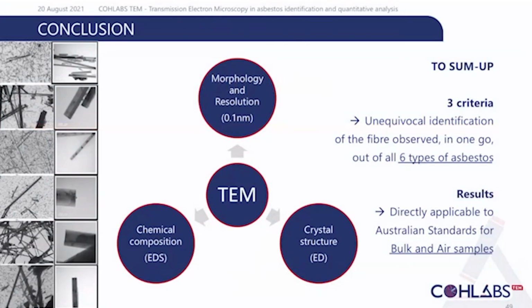So in conclusion, TEM gives access to those three criteria I've just mentioned: the chemical composition given by EDS, the crystalline structure given by the electron diffraction, and the morphology thanks to the high resolution of this microscope, down to 0.1 nanometers. Those three criteria give an unequivocal identification of the fiber observed in one go, and out of all six types of asbestos. And the results we have can directly be applicable to the Australian standards for bulk and air samples.